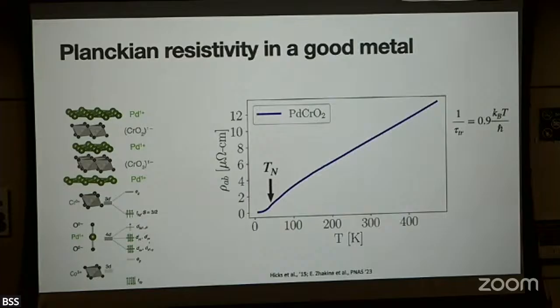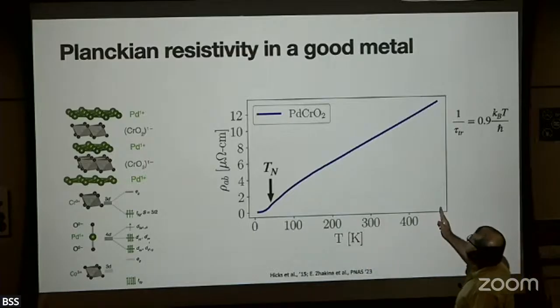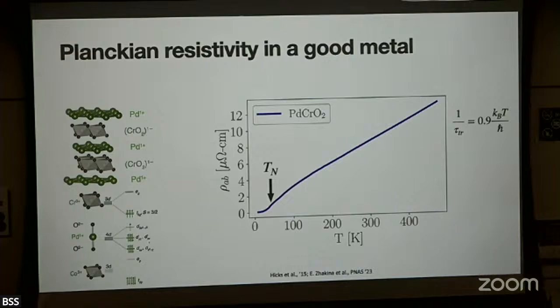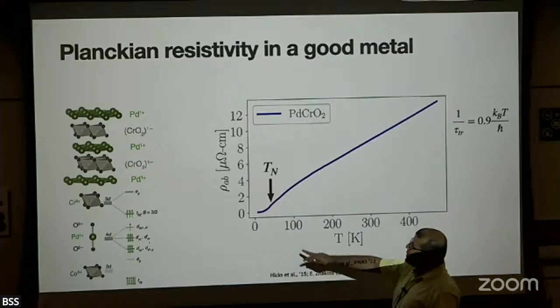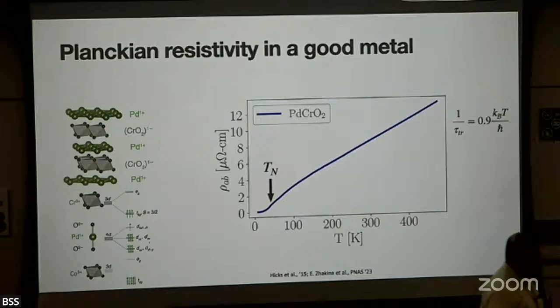Okay, and so this is what transport looks like in palladium chromium oxide. So at least there is some intermediate range of temperatures. This is limited by, I believe, the temperature of the furnace. And it just goes on and on up until that temperature. If you do the same Drude-like analysis, you get a scattering rate that's Planckian with an order 1 coefficient. Now, if I just gave you this compound, you would say, well, why not phonons? This might be consistent with phonons. I forgot to say that there exists some temperature around 40 Kelvin where the local moments in the chromium layer actually order. Yes?